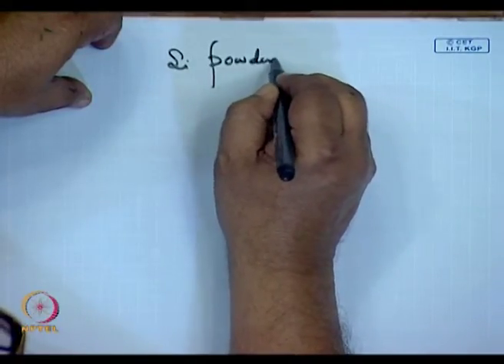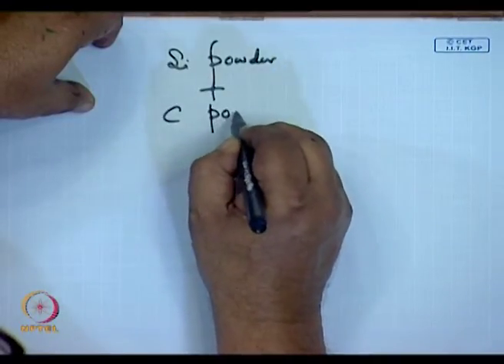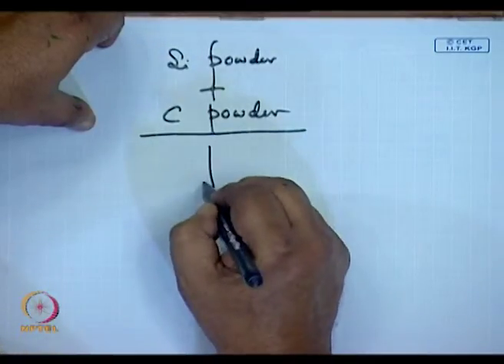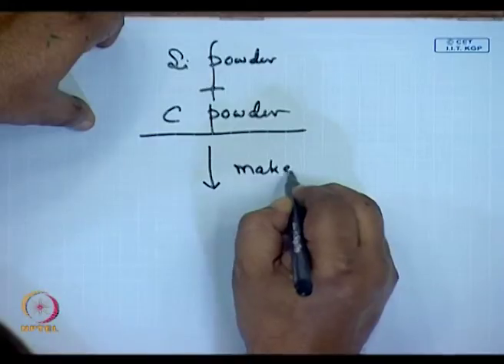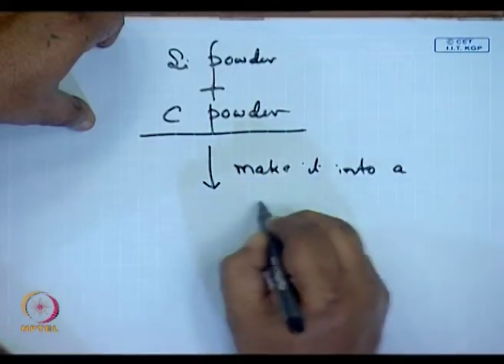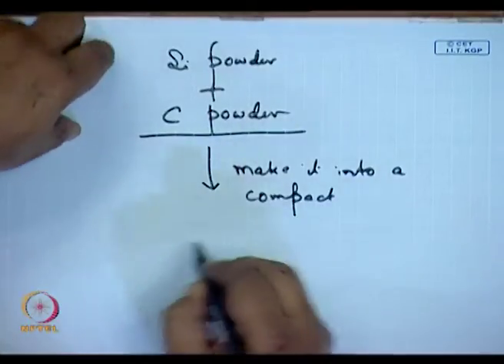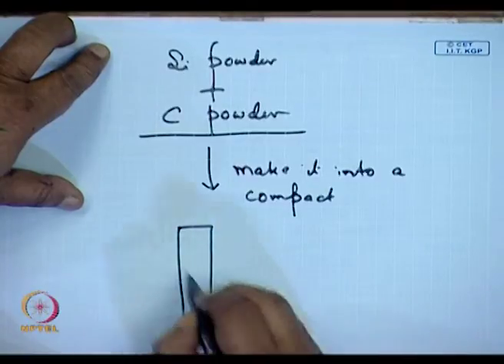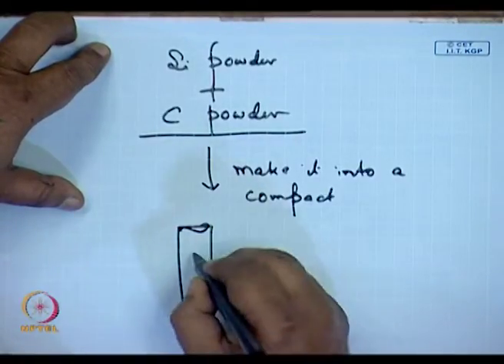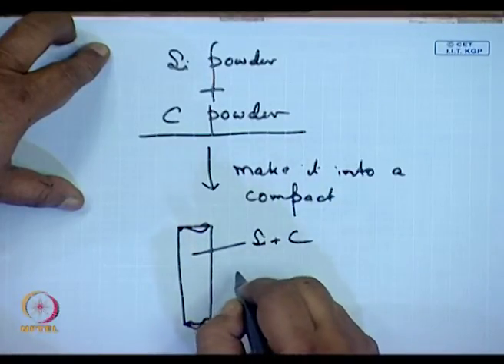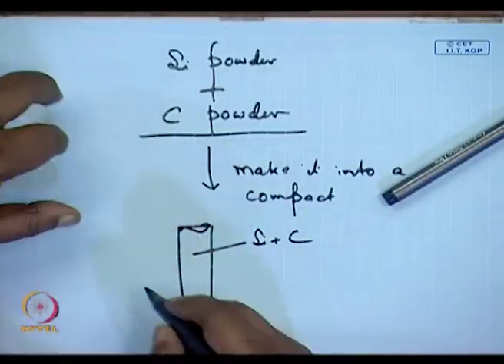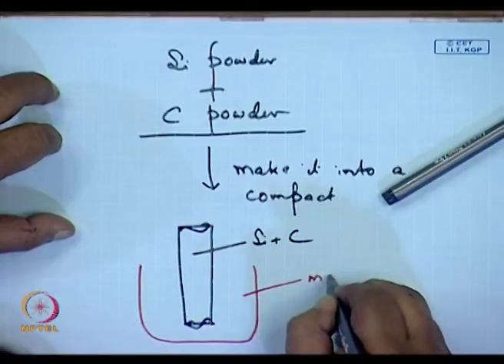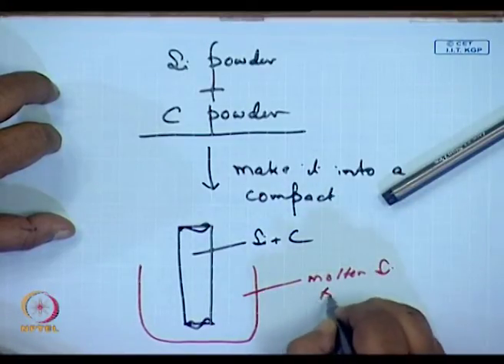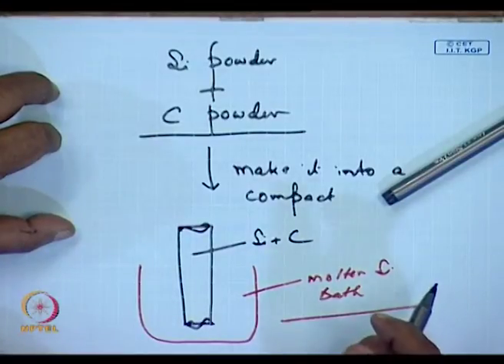One of the methods that we do is we take silicon powder, add to it carbon powder, make it into a compact. Let us assume it's a rod which has got silicon plus carbon, and the whole thing is immersed in molten silicon bath. All of this, of course, under oxygen free conditions.